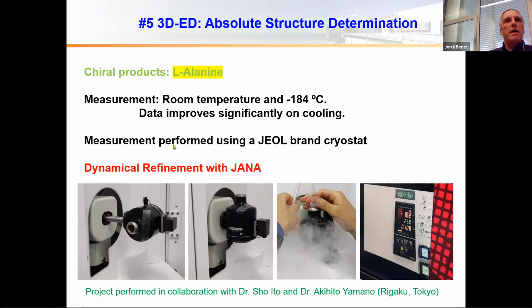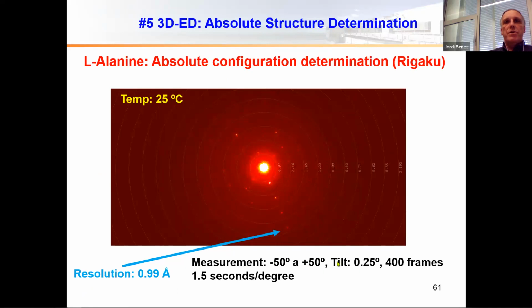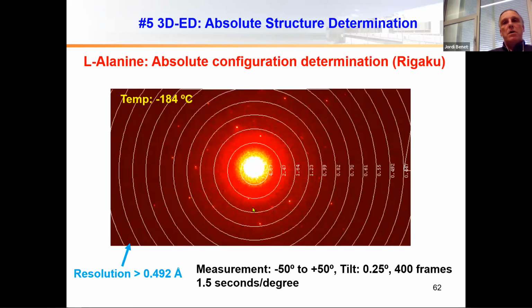So we took our L-alanine and went through our system, cryo-prepared, and did some measurements. First, we measured at room temperature, and we got a good data set at room temperature with a low resolution of 0.99 angstroms. By cooling down several similar systems using the JEOL cryo system, we got excellent diffraction patterns, up to resolutions of 0.49, so we can still see reflections here at the outer border of the diffraction image, and collect data sets.